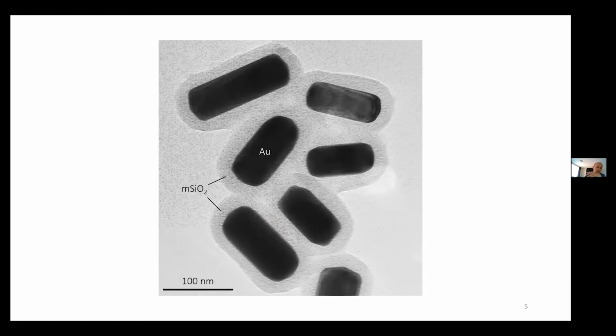And as I mentioned before, we want to generate fluorescent products that are generated at or close to a gold surface. But we also know that metal surfaces are good at quenching fluorescence. So if a fluorescent molecule is very close to this gold nanorod, there's actually quite a high probability that I wouldn't detect the fluorescence in the far field using a microscope objective.